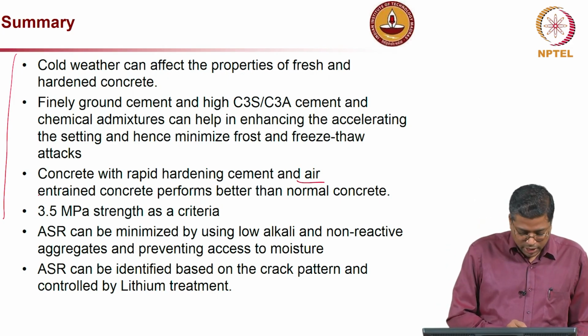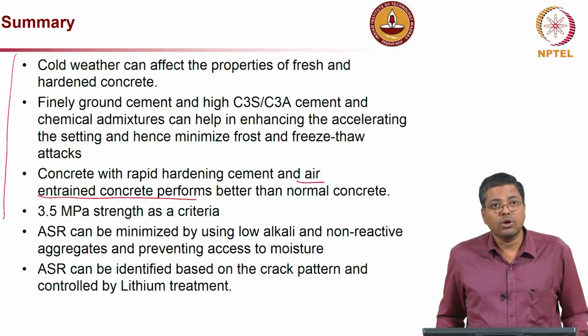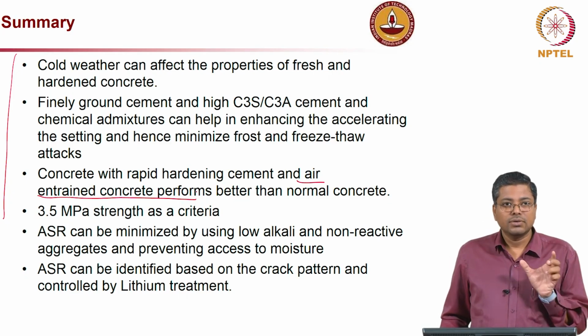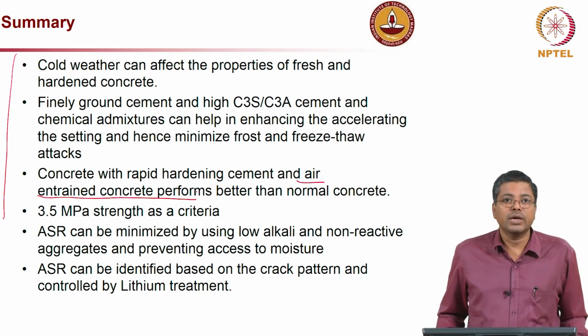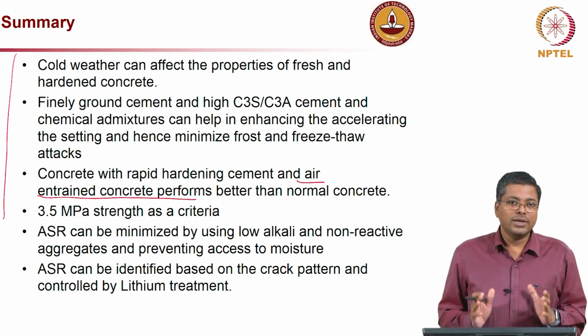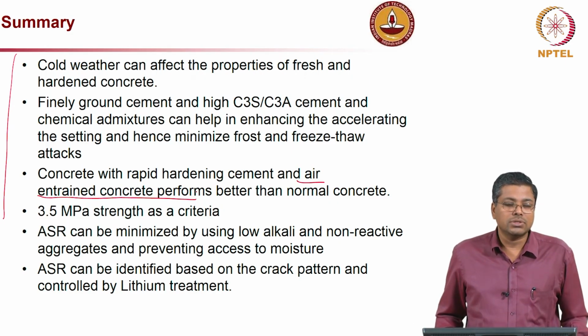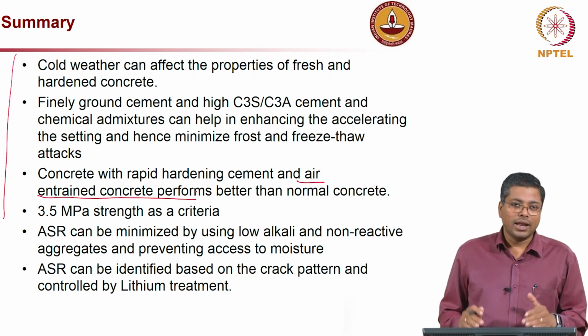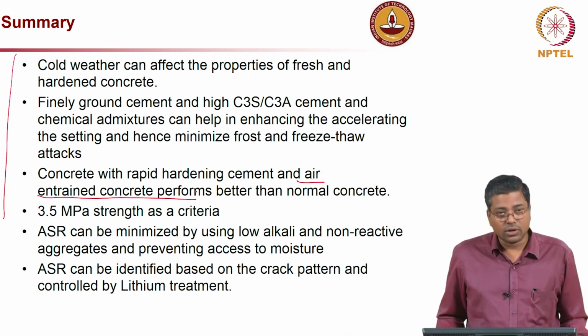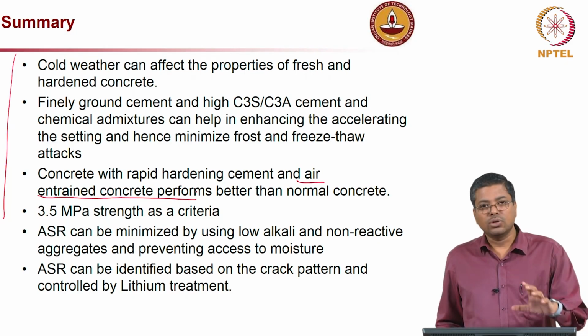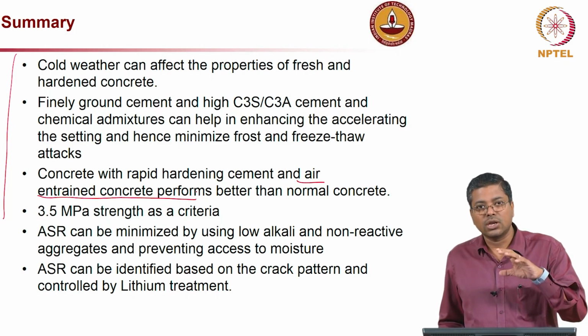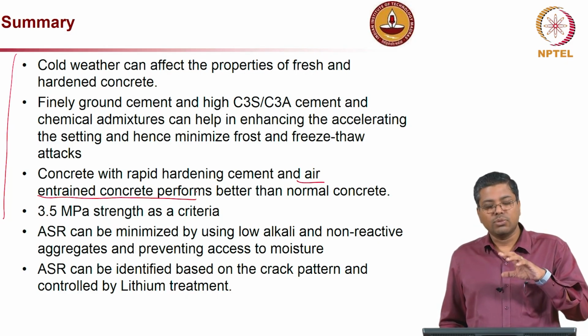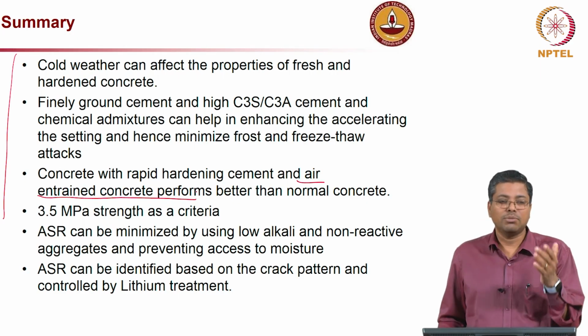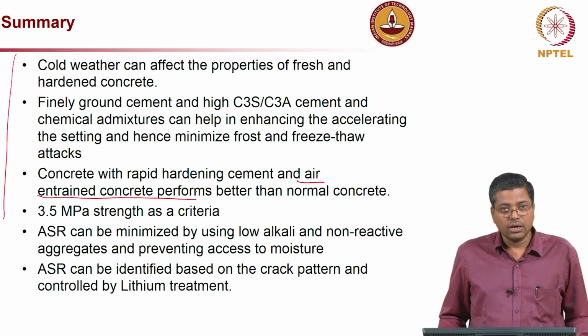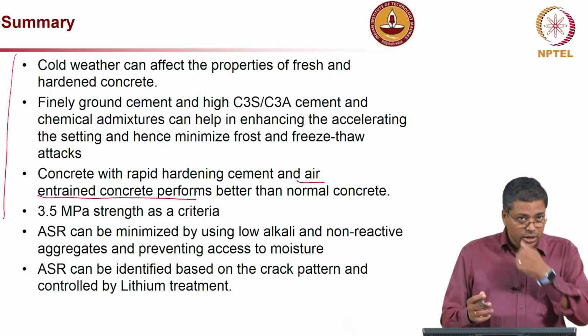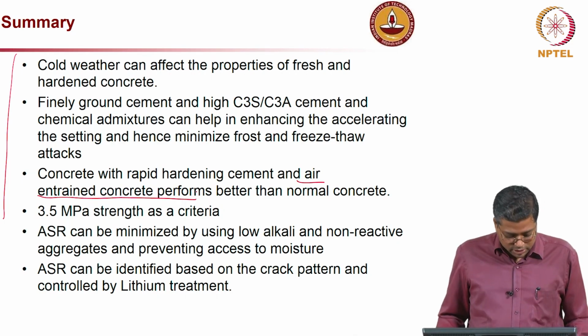So, here air entrained concrete performs better than normal concrete, and this figure of 3.5 MPa strength. You should ensure that the concrete achieves 3.5 MPa strength, and then further protection of that concrete is essential by ensuring that sufficient moisture level is maintained, and at the same time sufficient heat is maintained. Then concrete will continue to develop further strength.